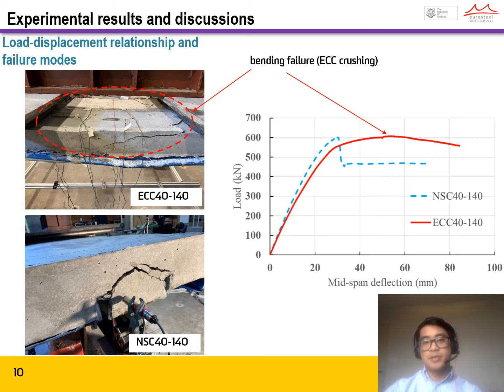Similarly, the NSC beam showed linear elastic behavior until the high-strength steel first yielded at its bottom flange at a load of 445 kN. It exhibited higher stiffness than the ECC beam, as NSC has a higher elastic modulus than ECC. However, unlike the ECC beam, which showed ductile flexural behavior, the NSC beam fell abruptly after reaching the peak load of 600 kN with a corresponding mid-span deflection of 30 mm.